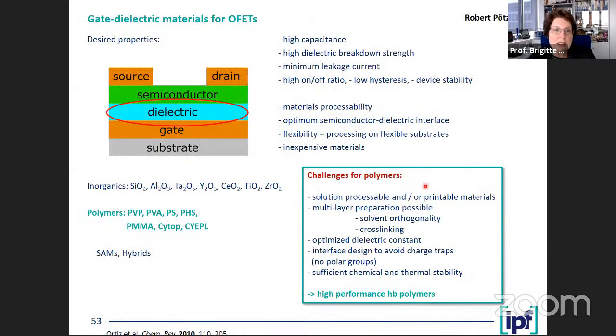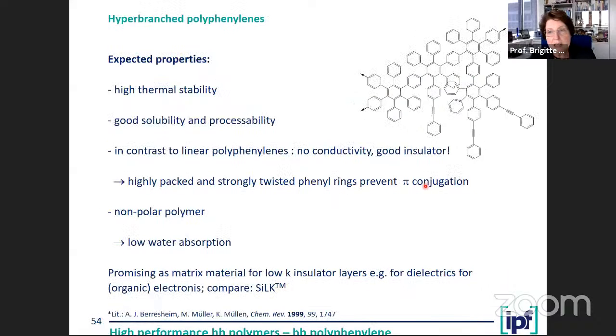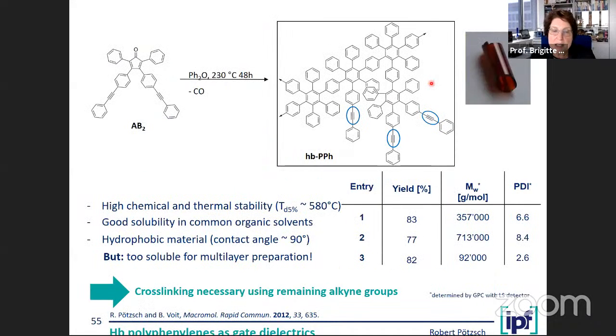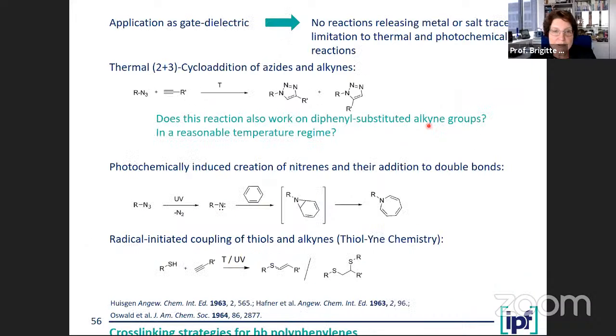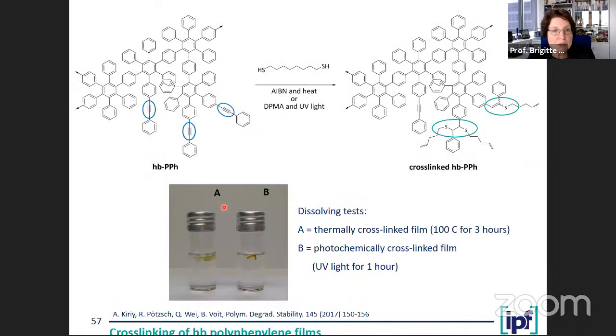So the last minute shows you only that that's of course only one part. For such electronic material, you need not just the semiconductor, you need also other material, dielectric material, for example. Here we contribute with hyperbranched material, for example, hyperbranched polyphenylenes, which we adjusted for cross-linking. So we have some cross-linking moieties in here, so triple bonds. And when you see triple bonds and are a chemist, you always think about the cycloaddition reactions, the click reaction. We did click reaction, but without the click, meaning we cannot use the copper because copper will totally destroy the electronic properties. So we used an old-time cycloaddition reaction, and it worked very well, and it can go thermally, but it can also go through photochemical induction.